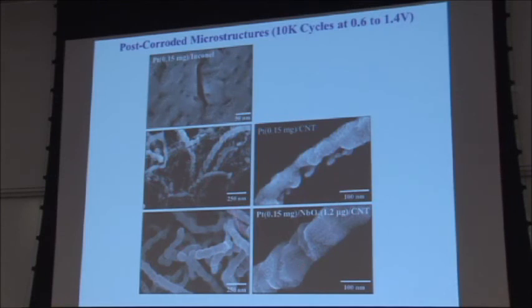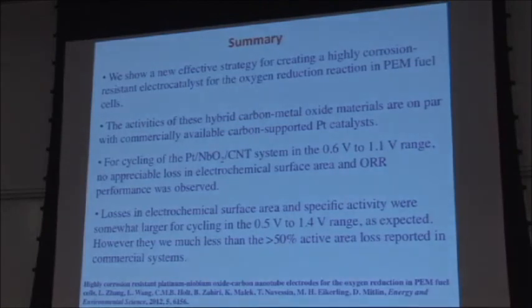These were taken at the exact same orientation, so these are both from the front side. But essentially, the microstructure is intact. And your loss of activity is really due to loss of these coarser crystallite faces in your microstructure. But not only does niobium oxide keep the platinum from corroding, it keeps the carbon nanotubes from corroding as well. So that's it. Summary, you could essentially read that yourself. If you want more information, it came out recently in Energy and Environmental Science. Okay, next.